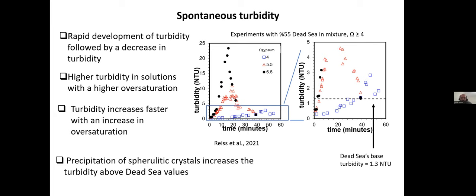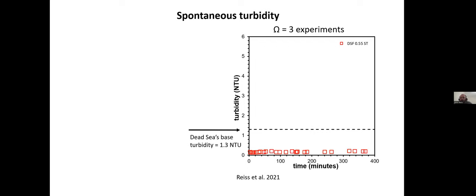event. If we go to the experiment with an oversaturation of 3, that again, I said, this is the highest oversaturation that could be attained simply by mixing the brines without any additional processes. Over longer time periods, I don't see an increase in spontaneous turbidity. However, if we look at the potential turbidity within this time frame, it does surpass the base value. This tells me that at the maximum expected oversaturation, again, excluding other processes that could concentrate the brine, even when sufficient amounts of gypsum have precipitated to cause increased turbidity in the Dead Sea, it doesn't happen spontaneously.